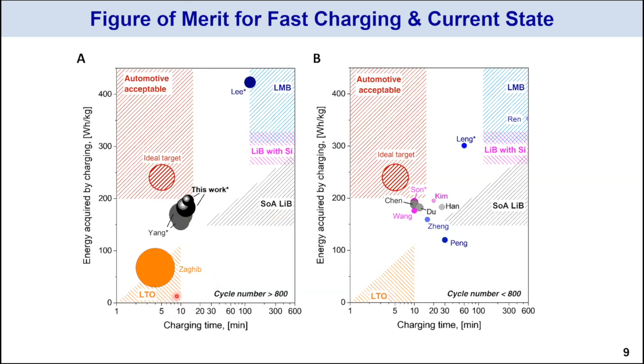And then we have a few other shaded areas. Here is the lower corner, the LTO chemistry, the battery using LTO material, which is a so-called no-strain material, so particularly suitable for fast charging. But the energy density is a little low and not very useful for automotive driving. But then if you replace the anode with graphite, you start to get this range of energy density with the lower limit more defined by LFP cathode and the upper limit by high nickel NMC cathode. And then if you further replace with silicon anode, you get another bump in energy density. And if you do lithium metal anode, you get a further increase in energy density all the way to 400 watt hour per kg area, okay?